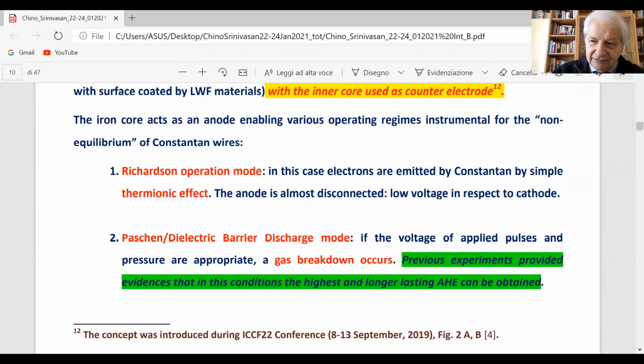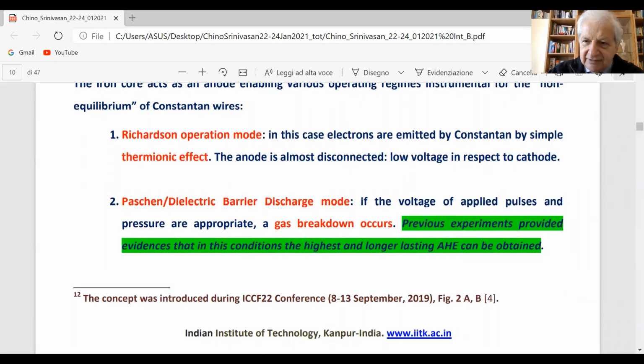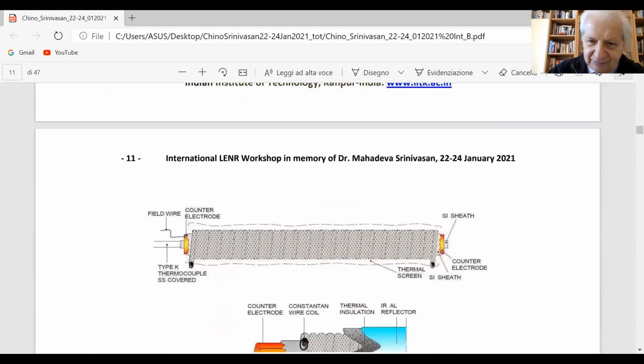The Richardson effect due to the high power injected means we have thermionic emission of electrons. And the Paschen regime means we have gas breakdown effects. In the experiments using AC excitation, we observed that at a specific gas breakdown voltage, we have a larger effect, enormous heat for a longer time. So our goal is to make more powerful effects than observed before.